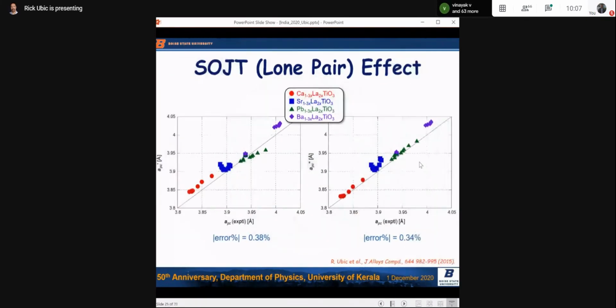Okay. Now, a couple of structural facts I talked about that we can see from this. First of all, I've graphed here A prime and A double prime for these perovskites. One thing you notice is that the fits are very good, but all the errors are slightly positive, with one exception: these green data points, which are the lead lanthanum titanate data points.